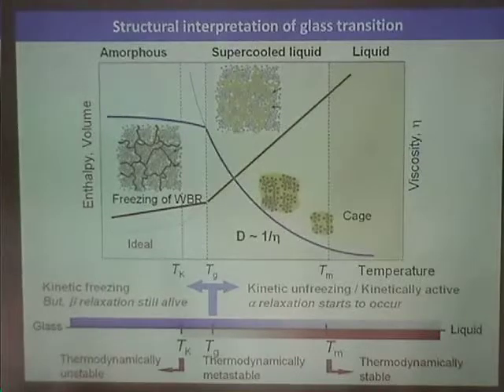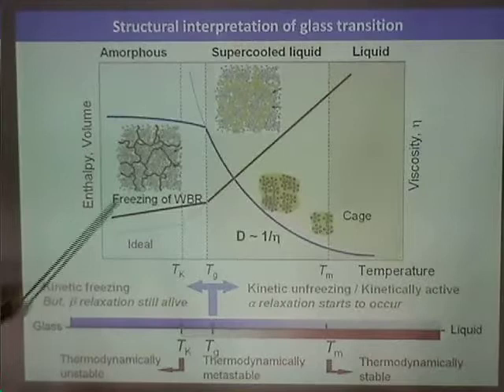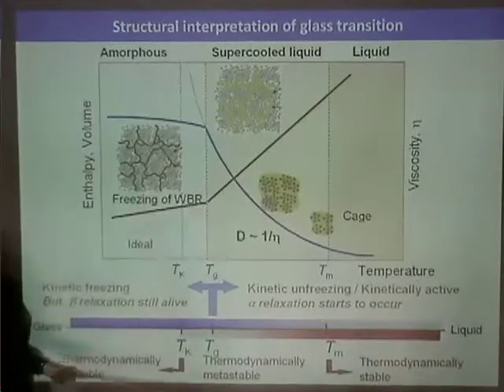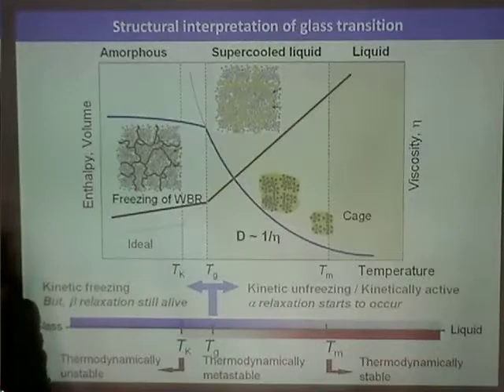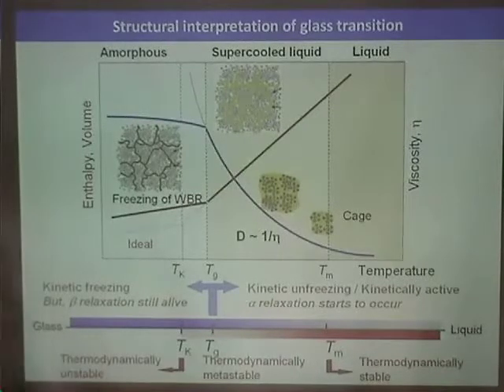How you measure it. No, I meant on your graph of viscosity there, did you really mean that the viscosity becomes lower than extrapolated? Yes. If you measure creep, because the structure is frozen. Usually we define 10 to the 12 Pascal second. Yeah, sure. So how do you define the viscosity of the amorphous material? You can measure the change of, for example, elastic property as a function of the temperature of the glass, and viscosity should correspond to the viscosity in the glass at different temperatures.